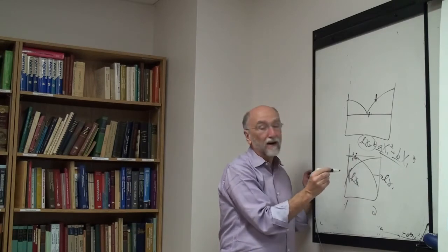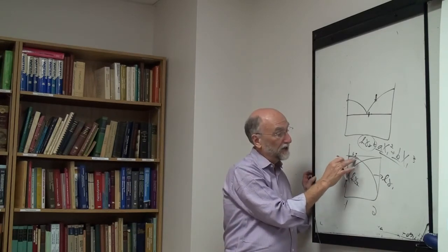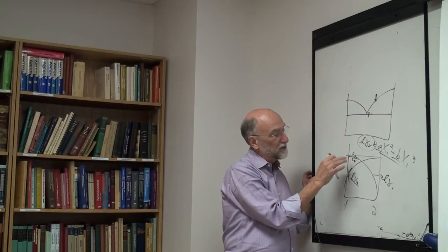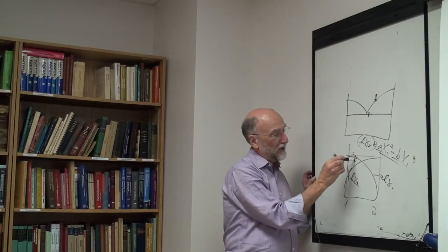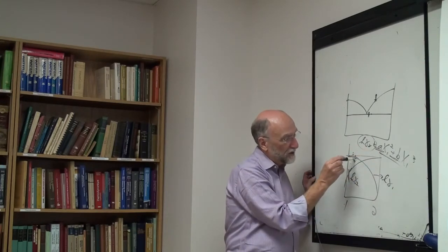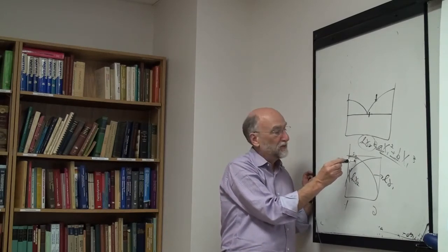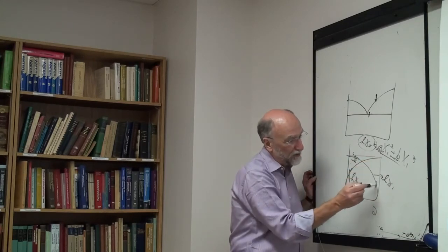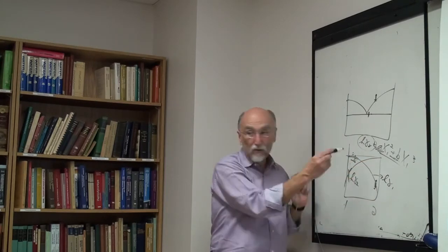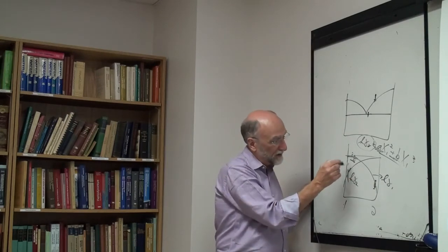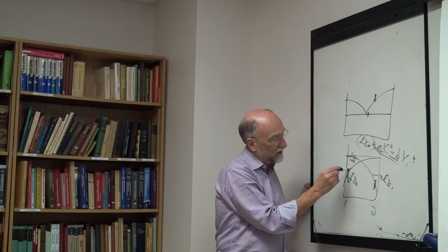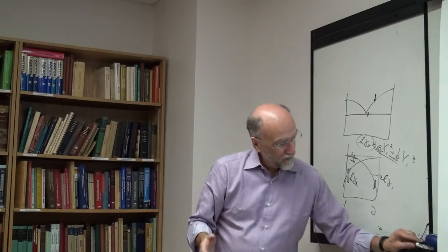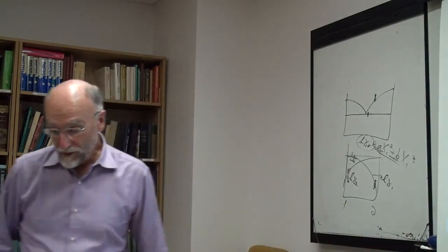If you've got a point here that's off, because somebody's made a silly measurement, it can be off by say 15 joules, but you're at 99% component 1, so it can't go like that. And yet this is going to really try hard to minimize that distance, whereas you should be ignoring that point. Whereas down here, where the points can be quite accurate, a very small change in the parameters can move this up and down, and it's not giving proper weight to that point. Or over here, if you have points like this, you'll find that the weighting here is not as important as this, but it should be the other way around. So that, and other things like that, are the problem with these optimizer programs.